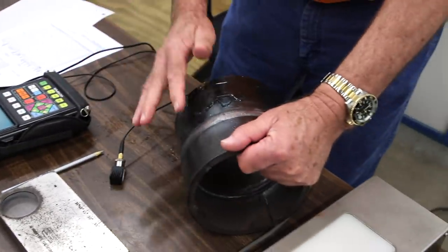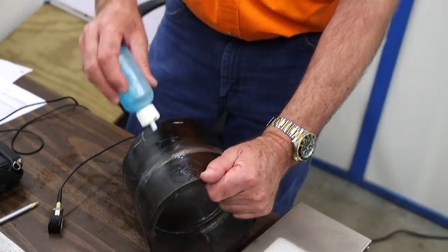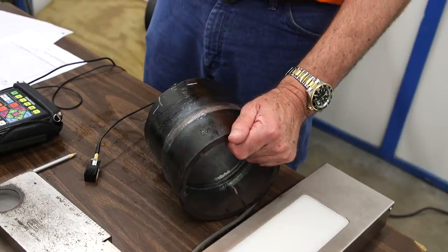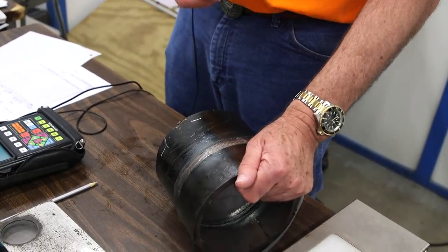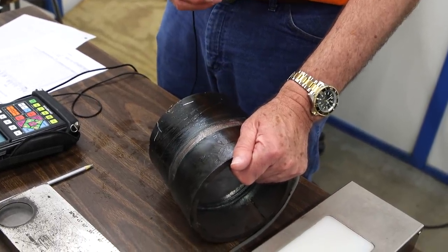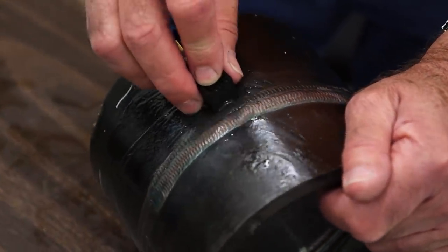Let's add some more of this stuff on here. It helps if you're doing this. I tell my students here, it really helps if you know a little bit about welding, and know what kind of possible defects you're gonna look at, depending on the technique. Whether it's submerged arc, it could be stick, it could be TIG. Each method potentially has its own little signature hickeys, let's say. So if you know what the technique is, you know what we're looking at, right? It makes your job a whole lot easier. This is TIG, so if I see something, I know right off, no, it's not slag.